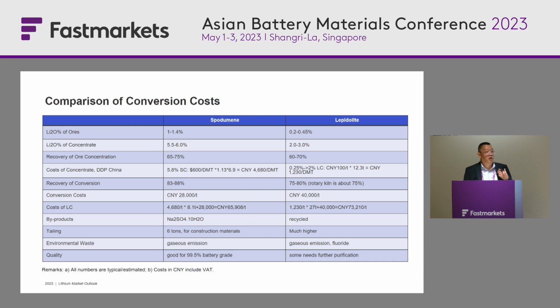And with the knowledge from the industry, you know the higher grade of feed material will give you lower cost, higher recovery, and so on. Okay. So we will concentrate spodumene typically to 5.5% plus. And in the past 2 years, when the price shot up so high, we could compromise to 5%. And any grade of spodumene concentrate below 5%, you'd better mix it with the 6%, the higher grade ones. So that's how we deal. That's why Chinese can take 4% spodumene from Africa and so on. So they mix it typically.